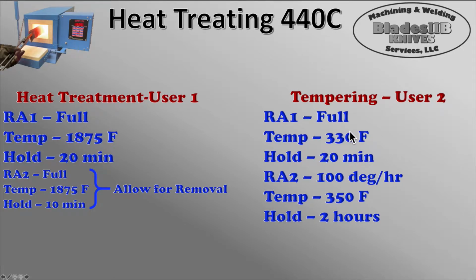So by following this step, I ramp it up to 330, I hold it there for 20 minutes, let the kiln fully warm up and stabilize, and then I ramp it at 100 degrees per hour up to the 350 degrees. So now it's taking it nice and slow for that 20 degrees in between, and then it stays plus or minus 2 degrees on that 350. Hold it there for 2 hours for my tempering. So that is basically the recipe for the heat treatment and tempering of 440C.